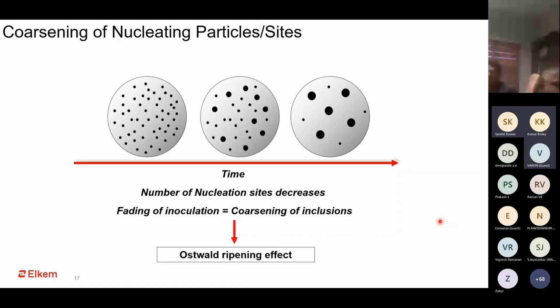Why does this happen? Why does the inoculant fade? When you add the inoculant, you actually create a lot of nucleating sites. You create a lot of locations on which the graphite would precipitate. But after time, these sites find it very difficult to hold on to their number or hold on to their size and shape, because they are very micro in terms of size. They have an inherent tendency to try and combine with the next one. The two sites which are close to each other will try and combine to form a bigger site. And once it becomes bigger, it becomes more stable. It becomes more safe. And this tendency keeps on happening with time.